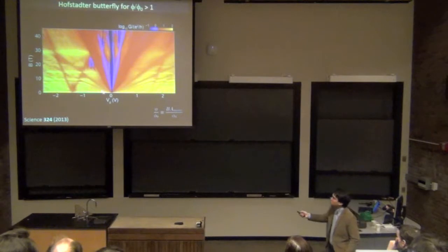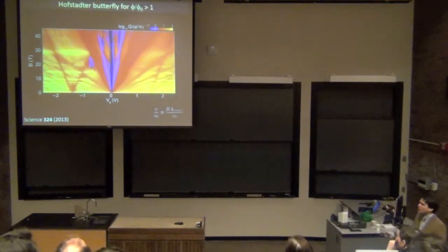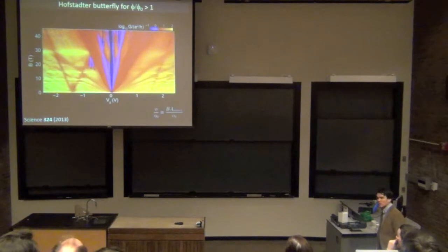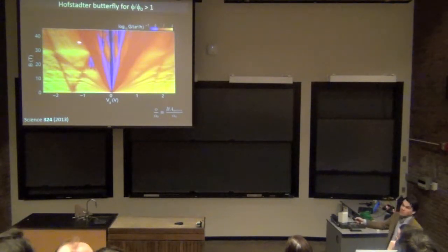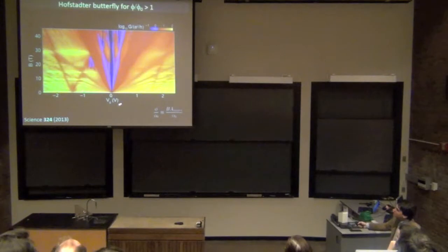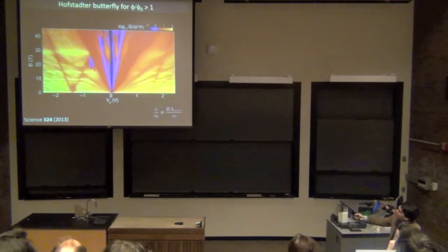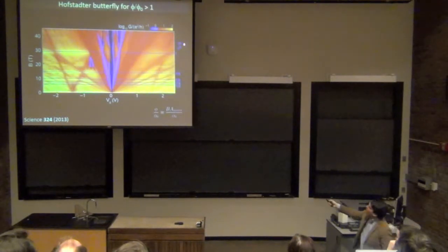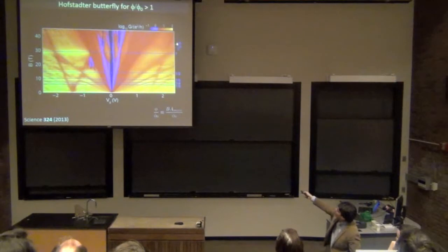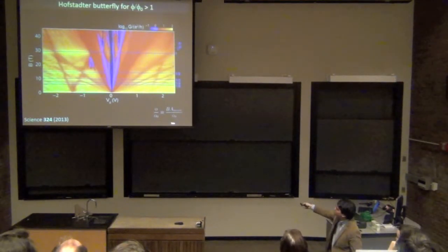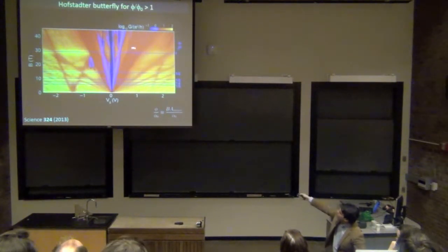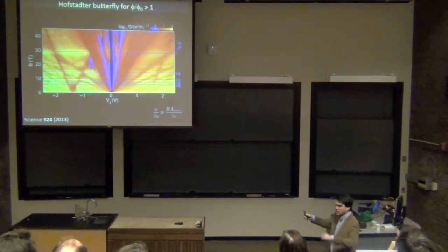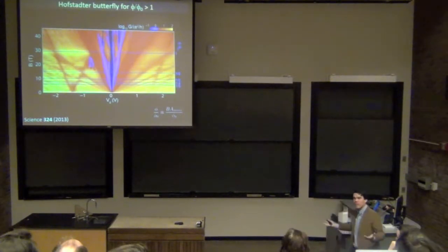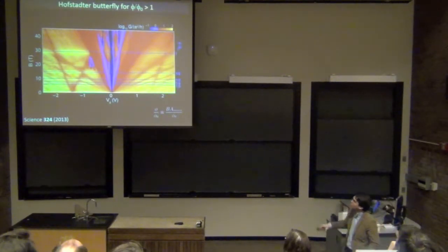We could only get to 13.5 Tesla, but we took our device down to Florida to the National High Magnetic Field Lab, put it in the largest DC magnet in North America, 45 Tesla, and what you can see is that if you concentrate on the central feature, you can start to see some pretty interesting things happening up here. This is now the magnetic flux in units of the flux through one of these moiré unit cells. You can see at this characteristic value of 1, where the magnetic length and the periodic potential match up, that you can start to see some really cool stuff happening up here.